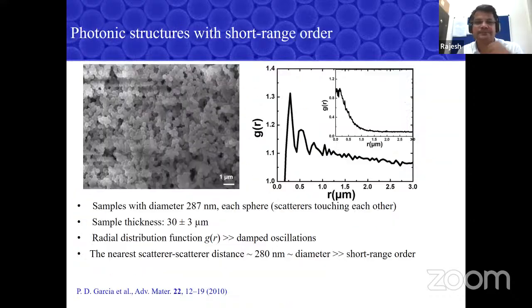So we took our ordered photonic crystal samples, and we did some crazy thing during the fabrication of that. And we got a structure where the disorder is not that random, but there is ordering locally, okay? Or we can tailor the disorder, okay? How do you know that the structure has a short range order, or locally there is order? So what we have is a picture of our disordered photonic sample.